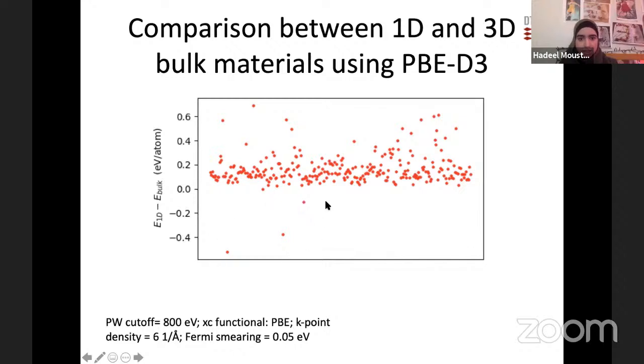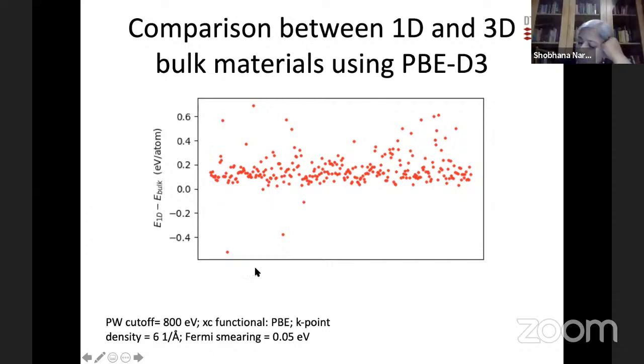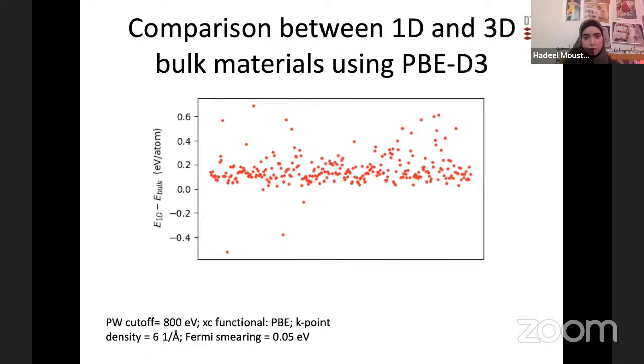Some of the materials have a negative value, which means that when we extract the 1D from the 3D, we gain some energy, which means that the 3D are unstable. And these three values are probably wrong, but our calculations are running automatically, and something wrong might happen. For the materials that are lying here, that means that the 1D are unstable and the 3D are more stable, so it's hard to extract the 1D from the 3D.